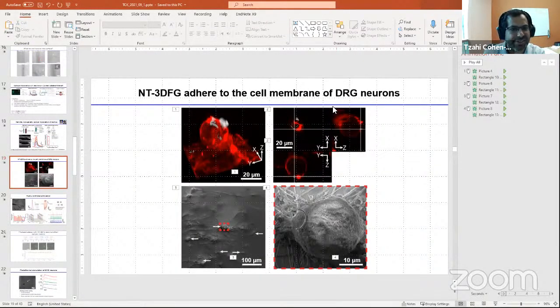What we did in this case, if you refer to the idea I mentioned over here, is use the technique developed by Dr. Wanunu at Northeastern, and we self-assembled the KF peptide just to render the surface of these wires positively charged through pi-pi stacking. We never tested the stability. The graphene itself is highly stable. We have data out there showing it is chemically and electrochemically stable as well, which is kind of surprising, to be honest, because the notion was that you have so many edges, it will probably degrade so fast. We have a paper showing that you can electrochemically cycle it for millions of cycles, and the chemical properties do not alter that much. That means the flakes do not degrade over like 7 million cycles of fast scan CV, for example.